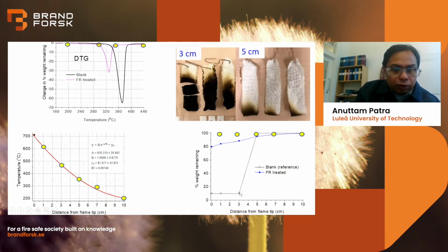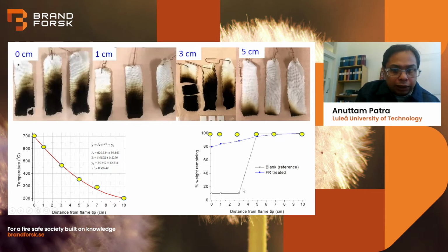And when we move closer and closer to the flame, the untreated cloth burns in a similar way, but for the treated cloth, there is only a very little decrease in weight. They never caught fire, or even if they caught fire, they self-extinguished in all cases. The 3 centimeter sample looks a bit black because I exposed it for longer, like 5 minutes, to check what happens, but the other ones are just for 1 minute. Otherwise, it would be a clear trend.